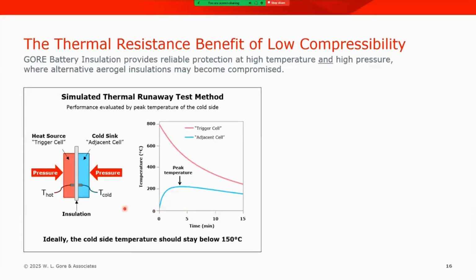Now, ideally, the hot side should stay hot and the cold side should stay cold. But the direct measurement of the impact of the thermal barrier material will be on the peak temperature that is achieved during this experiment. So we're going to take thermocouples on both the hot side and the cold side, and we're going to measure the temperature decay over the duration of about 15 minutes.